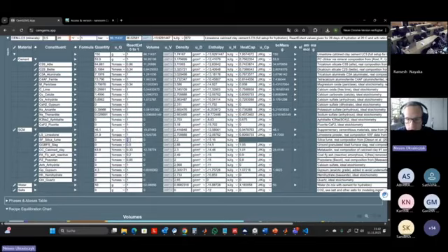So if you have some unreactive part in your fly ash, just put, I don't know, you have 90% that will react, so you should just put 0.9 here. And the rest is not reactive, and this can be then your fly ash.